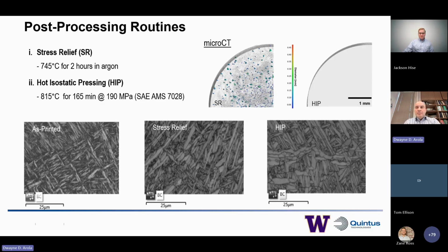All right, so just to make sure I'm complete about what takes place as a function of those two heat treatments, again, it's either a stress relief that's conducted in argon or the HIP treatment. We start with, on the left-hand side, the as-built condition. This is our standard Widmanstätten microstructure of acicular grains, alpha and beta ribs. As a function of the stress relief process, we get a little bit of coarsening, and that's exactly the same as we see for the HIP treatment, conducted at a little bit higher temperature and a little bit longer time, so you see a little greater amount of coarsening. And that shouldn't worry you. We don't get recrystallization. We only get the annihilation of the smallest portion of the alpha-beta interfaces, and then a degree of coarsening that results.